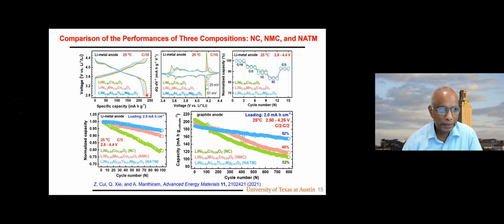So now a few things again here. When we go from NC to NATM, there is a decrease in the capacity, as I said earlier, and also small changes in the voltage. The peaks, as you see here, 25 millivolts more, and when you go to NATM, 51 millivolts, and we don't see much change in the rate capability. This is the cyclability with the lithium metal anode. You see, obviously NATM cycles better, but sometimes the cyclability could be due to a lithium problem or a cathode problem.